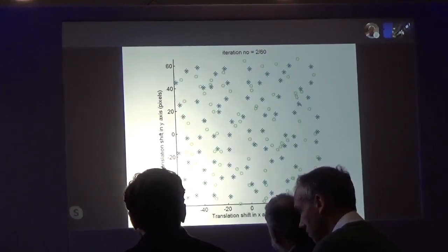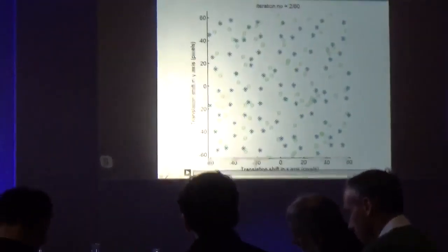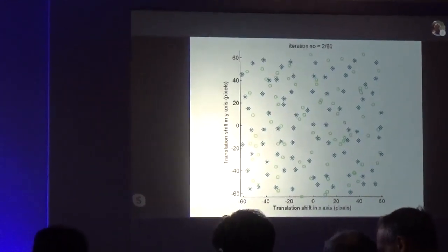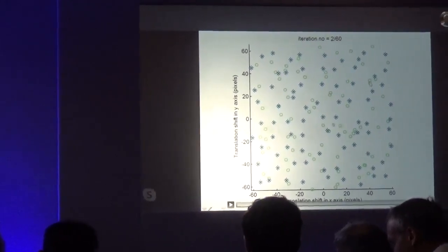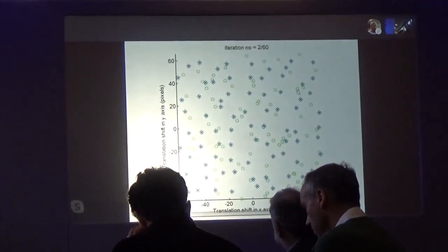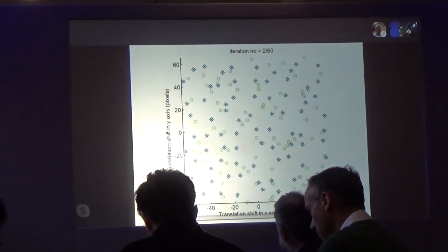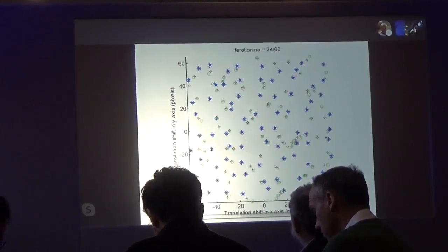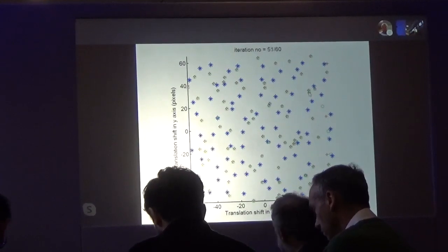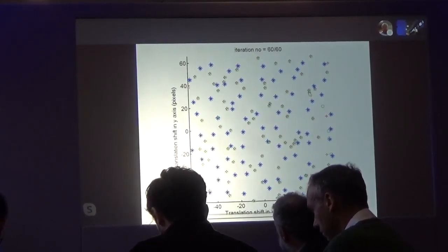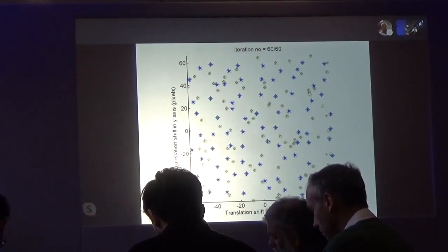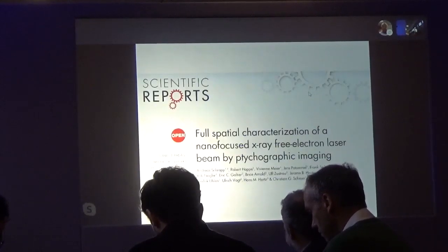And we know that in conventional ptychography, we can refine our knowledge of the illumination positions, which in this case are green dots, starting from our guesses of where we think the illumination positions are. And if we run this calculation, you can see that during the process, we actually solve for the probe position. So that's a possibility. Even if we're not in control of the beam very accurately, or at all, we can still use the ptychographic principle to get an image out.